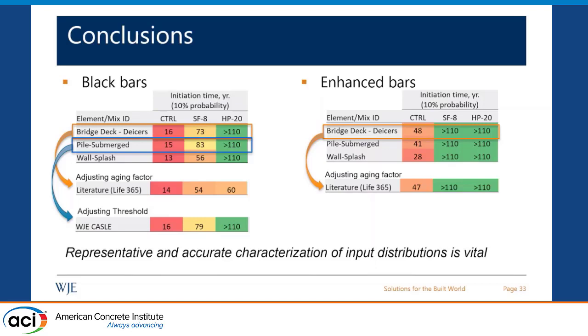So here, I'm summarizing the cases that we ran. When we looked at the aging factor, you see a big difference between the assumptions of the data that we're given as part of the input parameters for this session, and the aging factor presented in the literature. And the same thing with the threshold, which also provided some changes with the predicted service life.